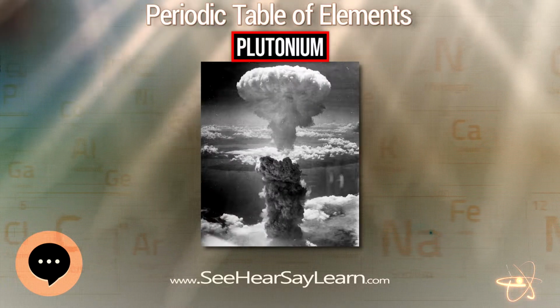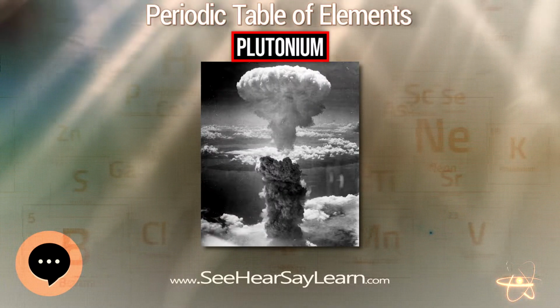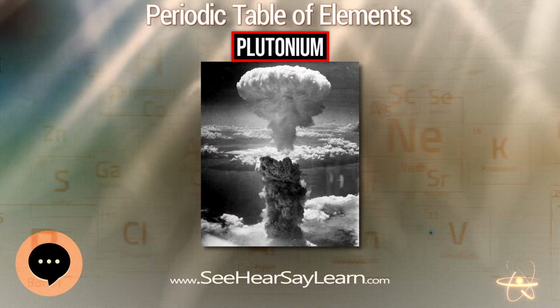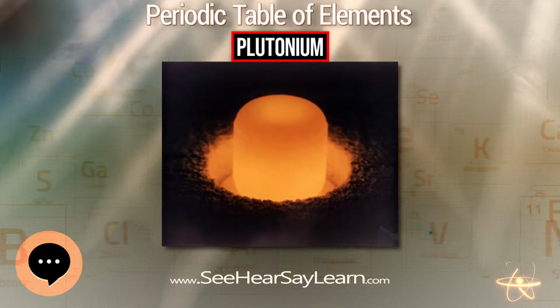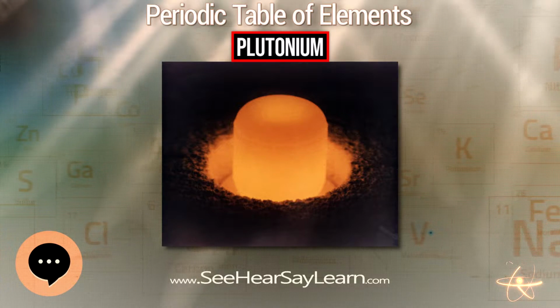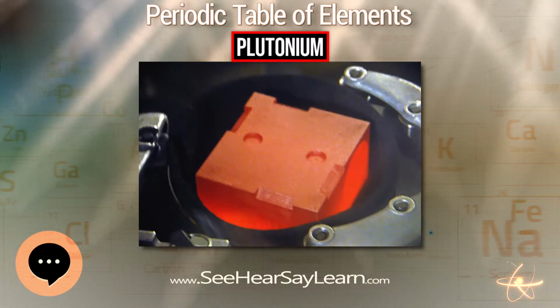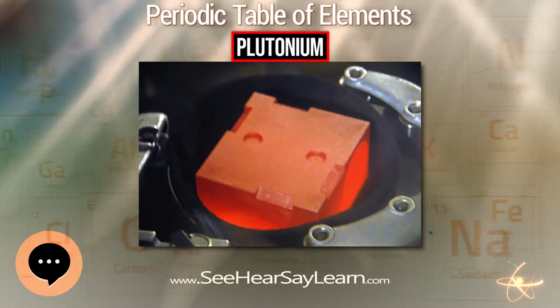Gallium, aluminium, americium, scandium, and cerium can stabilize the delta phase of plutonium for room temperature. Silicon, indium, zinc, and zirconium allow formation of metastable delta state when rapidly cooled.